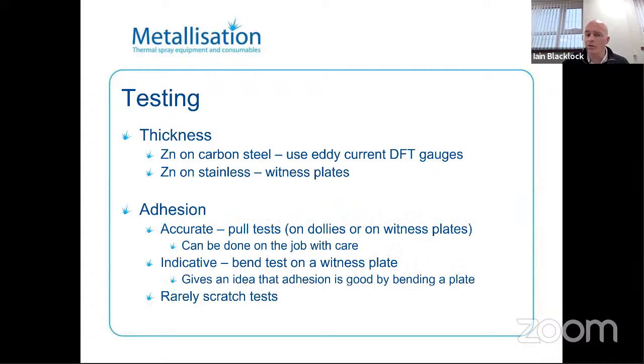As far as adhesion goes, this is quite accurate. It's a destructive test though, so it's pull tests using dollies on witness plates. Can be done on the job, but with care, but generally this is done on a plate which is sprayed at the same time. We use bend tests on witness plates, so this is where we spray a steel plate and we'll bend it over a mandrel, and you're looking for the coating to bend with the plate so that it just shows that you've got good adhesion and good cohesion within the coating. And rarely we have scratch tests, but in the industry, that's probably not one that's used very widely.